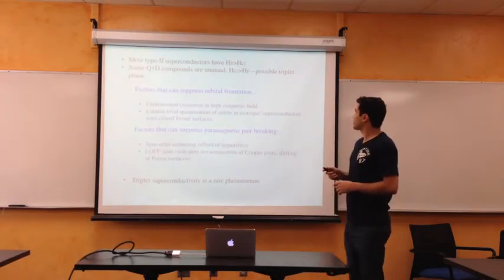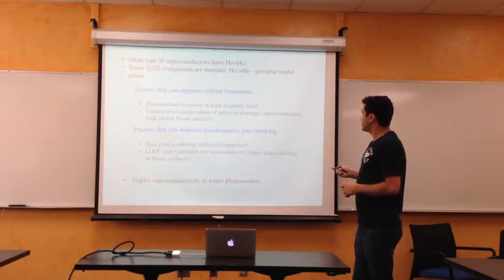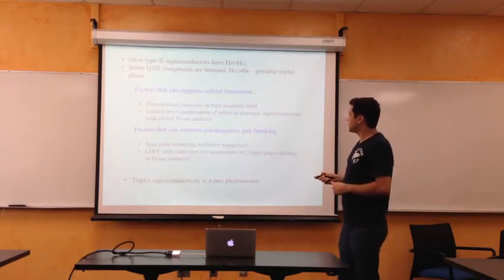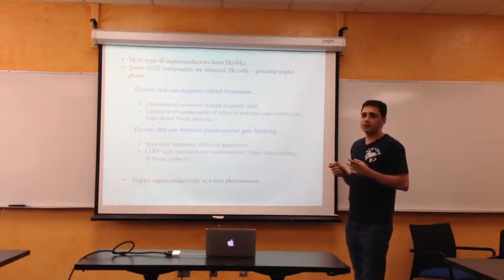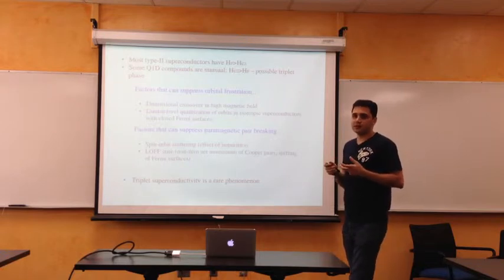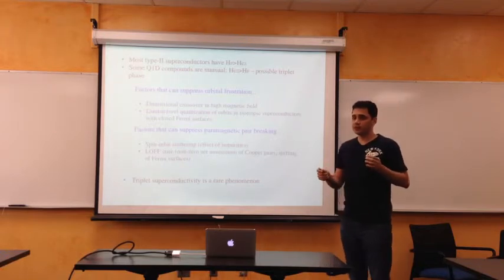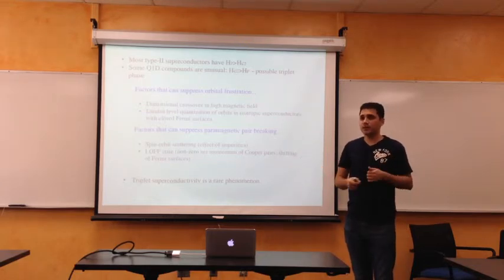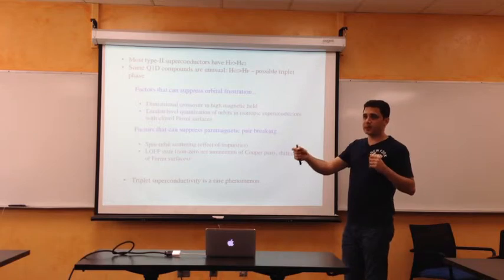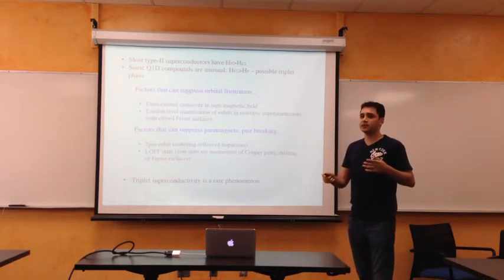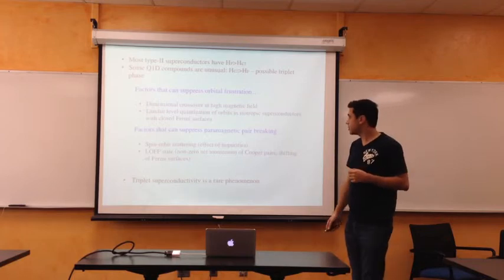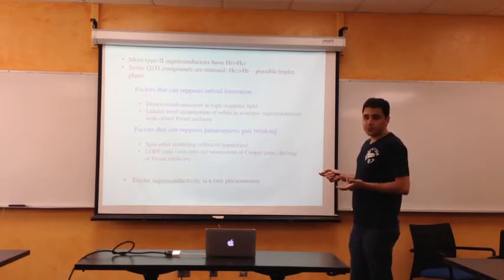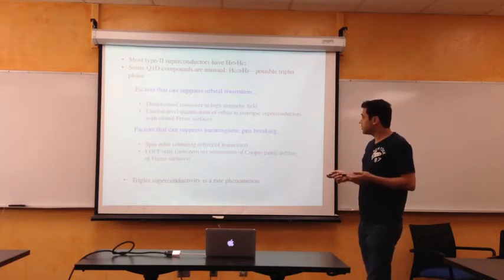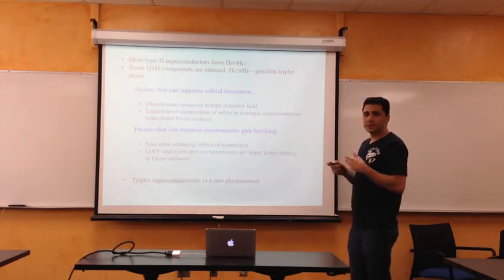So far so good? Okay, so what are the factors that can suppress the Zeeman splitting? One is spin orbit scattering. It seems that this material has very little effect coming from impurities. It has been measured experimentally, and the mean free path has been extracted, and it looks like the spin orbit mean free path is 2 orders of magnitude greater than the Boltzmann transport length. So the superconductor is in a pure limit, and spin orbit scattering is almost negligible.